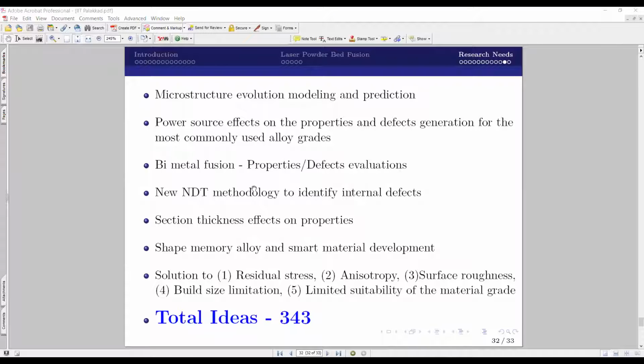Power source. How about if I print a component with a laser or electron beam or electric arc, whether the property remains the same or the microstructure remains the same or defect generation remains the same? No clarity. There are chances that some kind of laser may be beneficial for, let's say, steel, and electron beam may be beneficial for maybe titanium. So these also can be categorized. This will help the designer to choose the right 3D printing process in the coming days. And going to the next level, like printing multi-layer materials or bimetal fusions and understanding the interfaces and their property and defect evaluations.